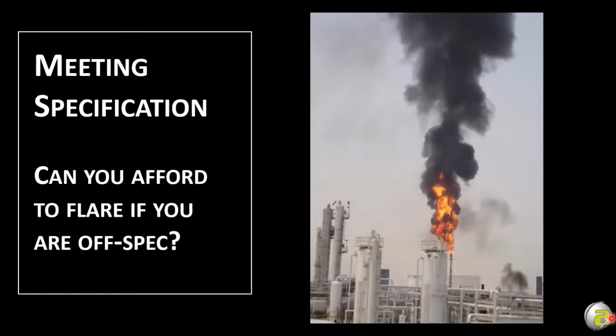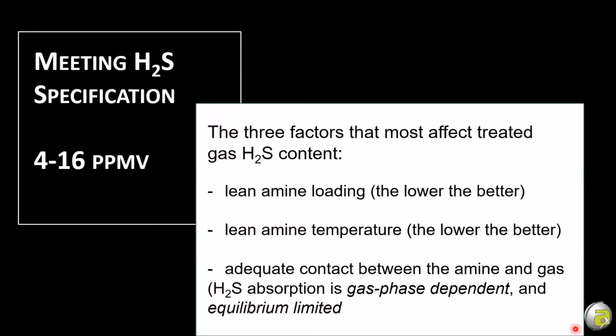This particular picture is from a plant in the Middle East that I did some troubleshooting work at, and this flare went for 6 months before they called us. So they were flaring 60 million of sour gas with lots of hydrocarbons for 6 months. I liked it because that's how I found the plant. I just followed the flare. And once we solved the problem and there's no more flaring, everyone around thought the plant had shut in, but it was actually processing properly. So you really don't want to have these kind of environmental excursions.